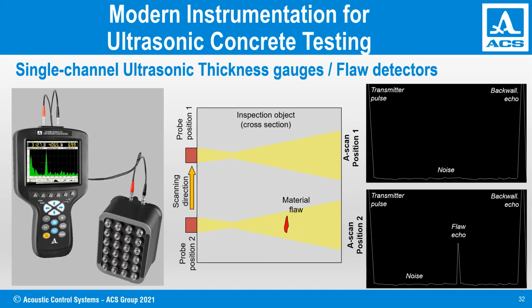We obtain echo signals, and the strongest signal we can ever obtain from the material is the backwall signal. That means the backside of the component. So if we are capable of catching the backwall signal and we know the sound velocity value, we can measure the thickness, and vice versa.